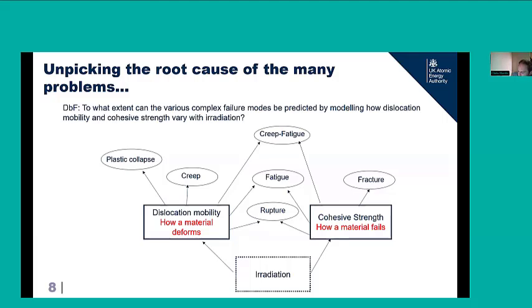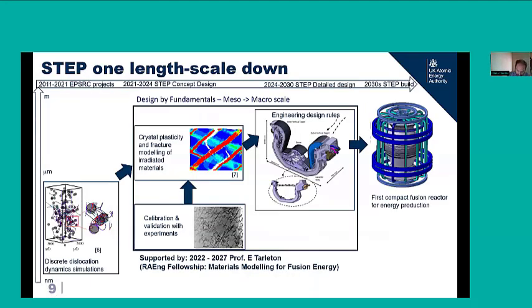And the other element of our project, which is somewhat unique, is that if it's unirradiated, we're not too concerned because you can test it a bit easier. So we focus a lot on the influence of irradiation. So rather than the sort of conventional approach of multi-scale modeling, our project is considering more of a top-down approach. So we take the tried and tested finite element analysis of components, which is accepted by nuclear regulators and stakeholders, and we take that same technology one length scale step down. So rather than modeling components, we're now modeling microstructures, and we're interested in finite element analysis and crystal plasticity finite element methods, and other complementary techniques within the finite element package that we can apply to best represent the deformation and failure of microstructures.